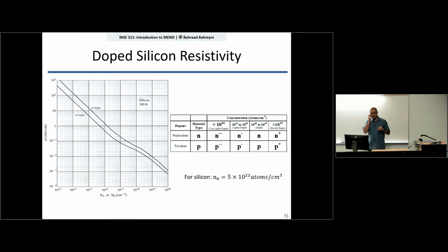And then only remember that for silicon you have about 5 times 10 to the 22 atoms per cubic centimeter. So even if you dope at the level of, let's say, 10 to the 18 atoms per cubic centimeter, that's the unit we normally use, if the number of dopants is that many, it still means that it's roughly 1 out of 50,000 silicon atoms that you've replaced with a dopant atom. It's a tiny fraction of the total number of silicon atoms that are there. You're talking about 1 in 1,000 to maybe 1 in a million.